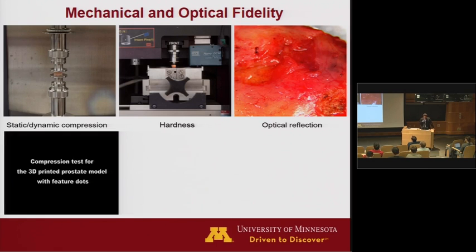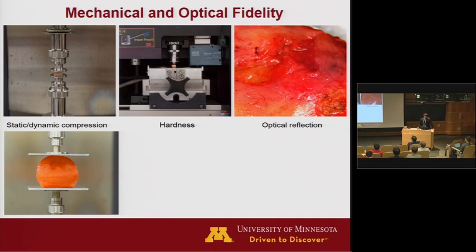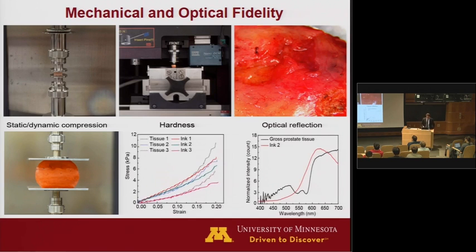We did these tests on them, and then what we can do is we can compare these compression tests and these mechanical tests on the tissue samples to the organ model itself. And these are not just physical tests. We also did actually a fair bit of modeling for this paper as well. But what you can see here is actually a pretty close representation and fidelity, again, between the mechanical tests of the inks and of the tissue samples that we obtained. We obtained 3 prostate samples and 3 different inks that we developed. And you can see in the low strain region, at least, you can see almost a perfect match between the 3 inks that we developed here and the 3 tissue samples that we obtained.